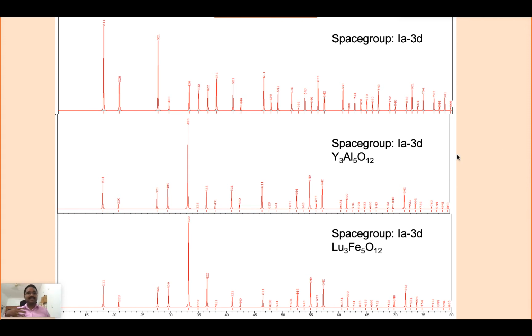But you see the difference. The first graph shows all the peaks for the space group. But when I come to specifically placing atoms, Y3Al5O12, yttrium aluminum garnet, when I place yttrium, aluminum, oxygen, you can see the peak intensity is different. Now you have to remember that table where peak positions were determined by a, b, c values. Now peak intensity is decided by the position of atoms. So when yttrium, aluminum, oxygen are placed in specific places for the same space group, the peaks are different.